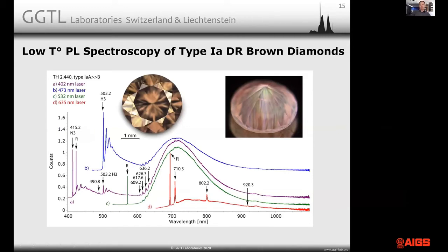Here you see the fluorescence image of this diamond, this pinkish brown diamond. You can see it's mostly pink with some green and some blue in some corners, and the correlating photoluminescence spectra. Now, these PL spectra have been recorded with a range of lasers, 402, 473, 532, 635. And the most interesting ones are the ones in the lower wavelengths, because you have the most information in them. You can see that this strong pink fluorescence is caused by a very broad band centered at around 750 nanometers.